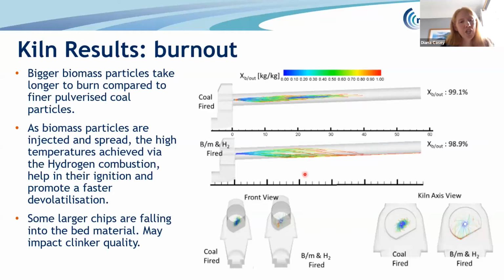But because it has a bigger chip size than coal, which is normally ground to micron-sized particles, these larger biomass particles continue burning as they travel down the kiln. Some end up on the surface of the bed, where they continue burning. You can see in this diagram, a cross-section of the end, some of the particles making their way into the bed at the bottom.